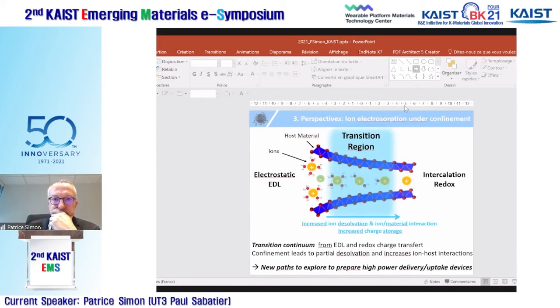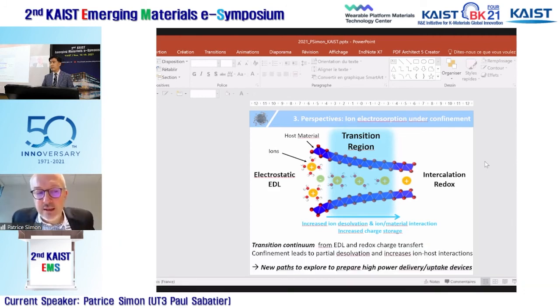I wonder if the capacitance due to confinement is similarly applicable to other van der Waals 2D materials? This is something where there is a recent paper published by the group of Veronica Augustyn in Nature Materials on MnO2, birnessite MnO2. This is a 2D material, and yes, as you can see, there is this kind of switch from a capacitive-like signature, which is based on redox reactions. So yes, this applies; it is at least applicable to other materials. And now we are trying to explore other materials, like 2D TMDs and so on, to see if we can find the same thing.